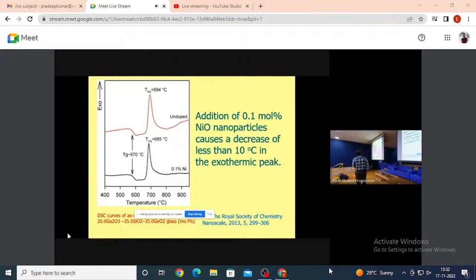And after that, at the high temperatures, there is the peak like this. This is related to the crystalline temperature at the high temperatures. This is the exothermic reaction. So here, this is undoped sample, this is doped sample. When we heat it, when we trace the DSC traces, then there is a shift of the crystallization temperature from 694 degrees centigrade to 685 degrees centigrade. That means the temperatures are coming towards the lower values. That happens in the nanoscale.